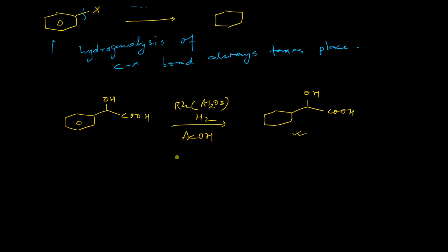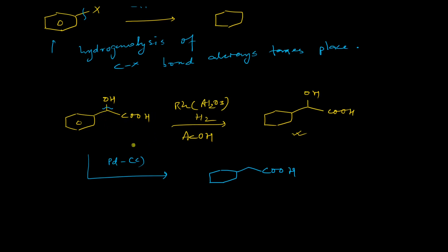However, if the question specifically wants a product where hydrogenation as well as hydrogenolysis are occurring at the same time, you must use palladium on activated charcoal. Always remember: whenever hydrogenolysis at the benzylic position is required, palladium is the choice. In presence of hydrogen gas and a solvent such as methanol or ethanol — no acetic acid or strong acid is required with palladium on activated charcoal — you will get the desired compound.